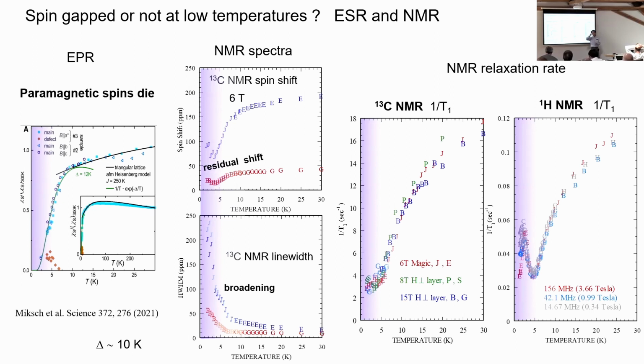In the very spin-active regions, we cannot align the nuclear spins on the very active electron spin site, because the spectral line is out of our NMR range. So the relaxation rate becomes comparable to the actual frequency. So this is a spin diffusion limited relaxation rate. But this proton NMR detects the average of all the relaxation rates.